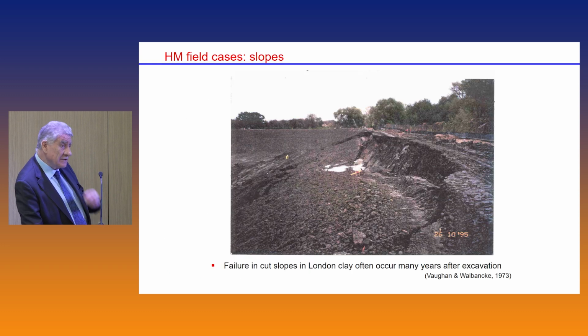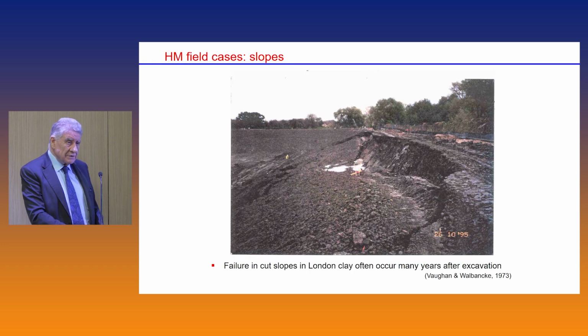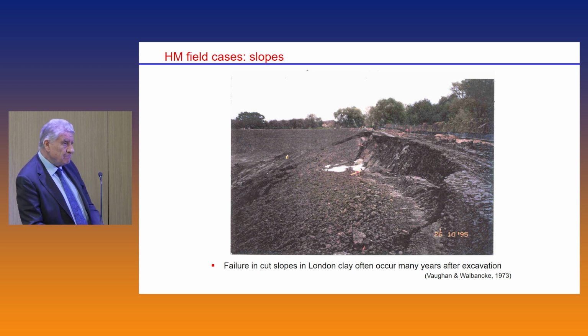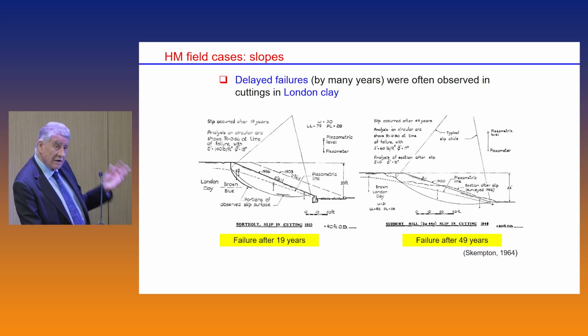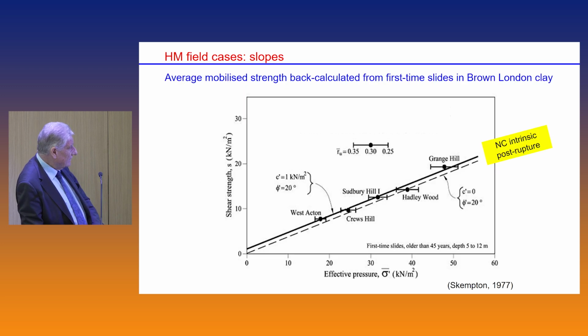The first one is slopes in London clay. I'm bringing this here, although it's rather a mature subject, because it has been extremely influential in developing the present ideas about progressive failure, brittleness, and so on. One thing that was puzzling the geotechnical community for some time is that the cuts in London clay failed. Many cuts failed, but interestingly they were failing many years after they had been excavated. For instance, these are 2 examples actually coming from Skempton's Rankine lecture, in which this one on the left, which is the Northolt one, failed after nearly 20 years, and this one in Sudbury Hill actually failed after nearly 50 years. And so that created a puzzle.